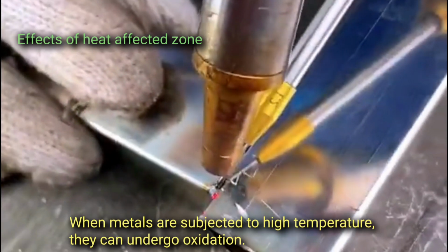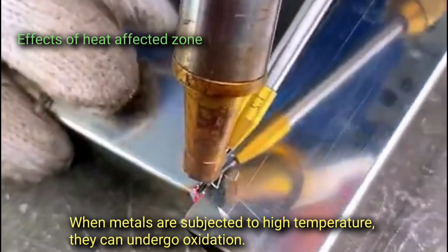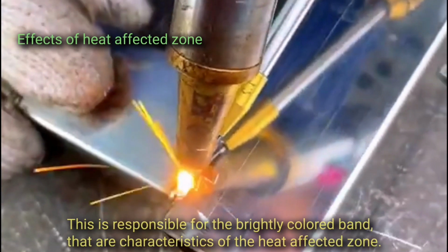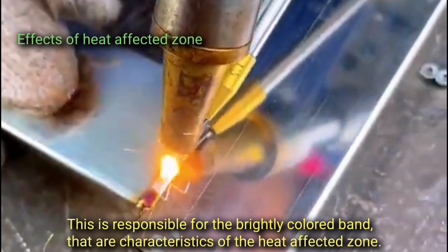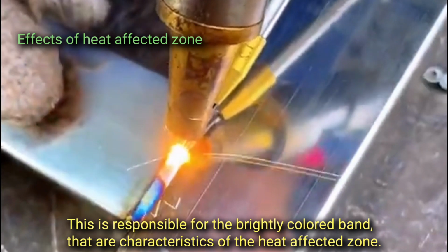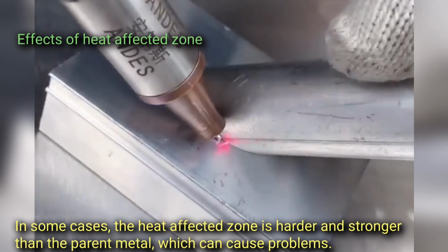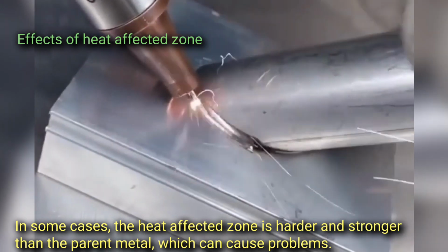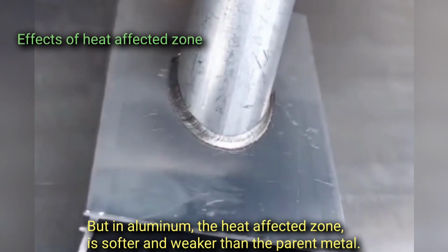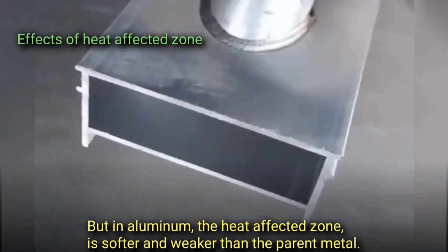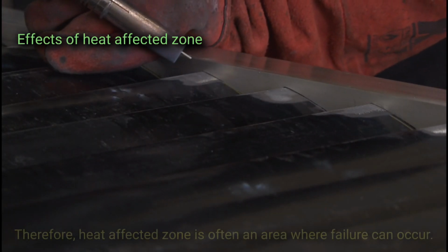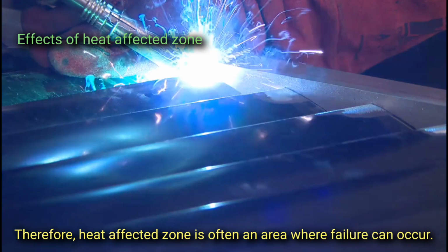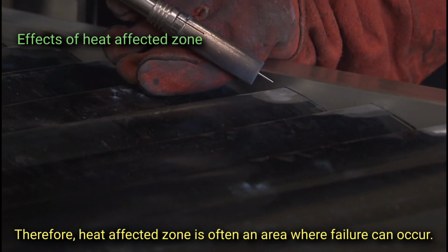When metals are subjected to high temperature, they can undergo oxidation. This is responsible for the brightly colored bands that are characteristic of the heat-affected zone. In some cases, the heat-affected zone is harder and stronger than the parent metal, which can cause problems. But in aluminum, the heat-affected zone is softer and weaker than the parent metal. Therefore, the heat-affected zone is often an area where failure can occur.